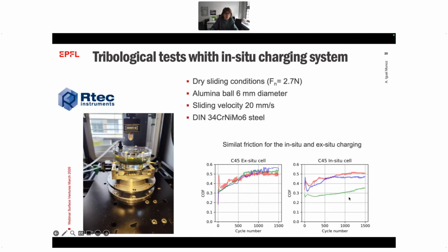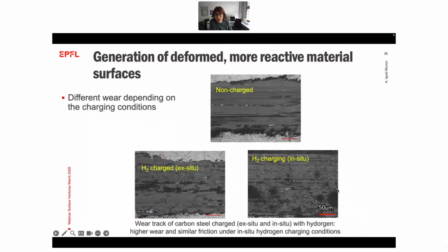Have certain scattered and slightly different coefficient of friction. What we observe then, when we have a look at the surface, the non-charged, the charged wear track of the charged sample ex situ, and the wear track of the charge. Sorry, this is charge ex situ, and this is charge in situ. We see that we have different wear depending on these charging conditions.